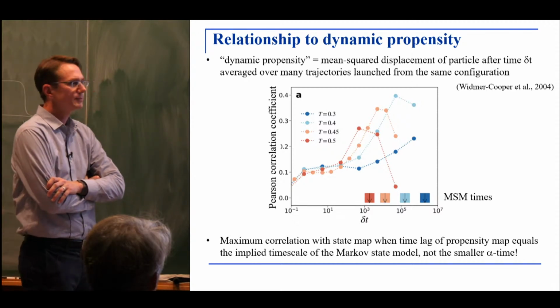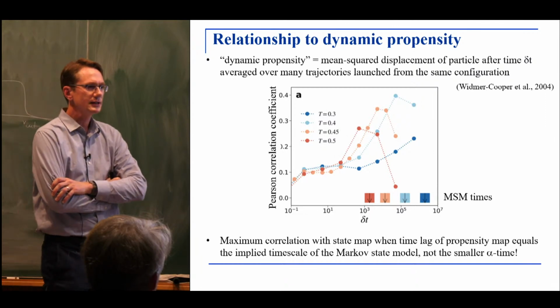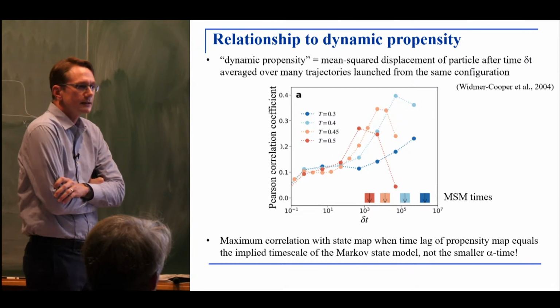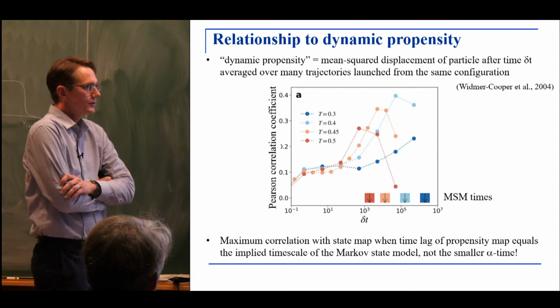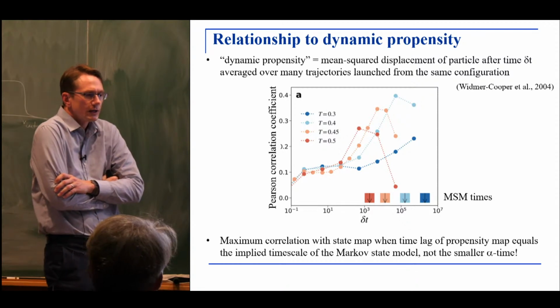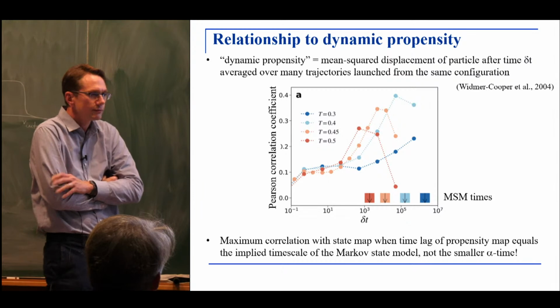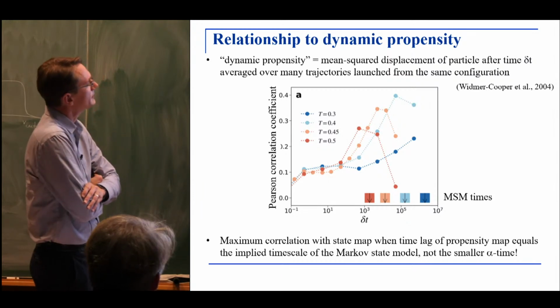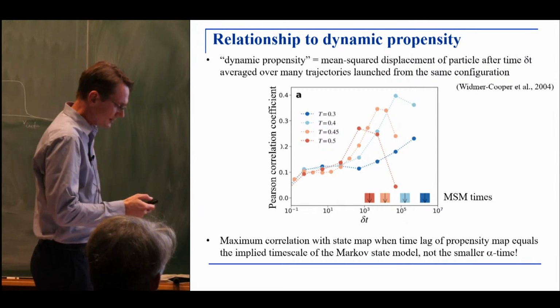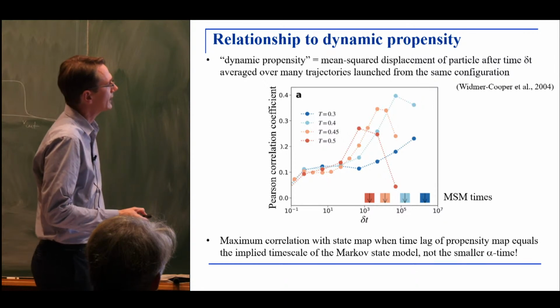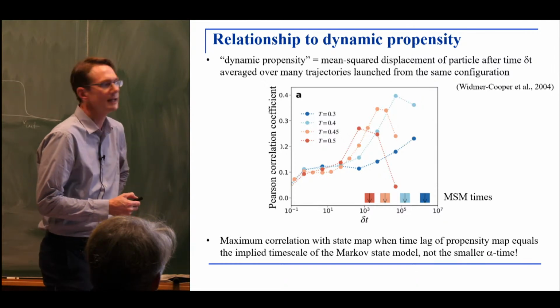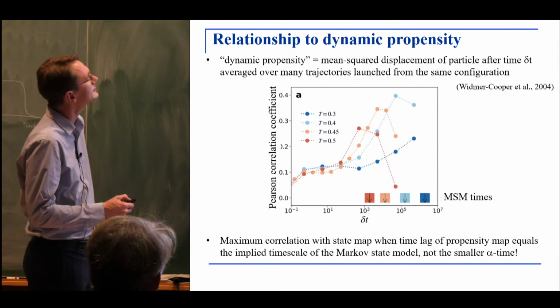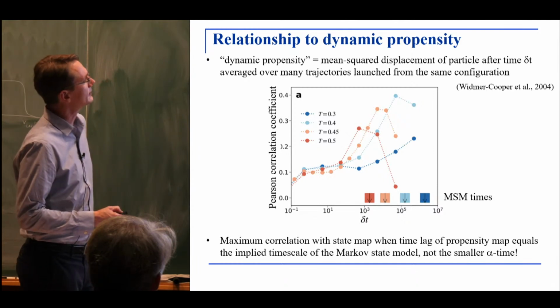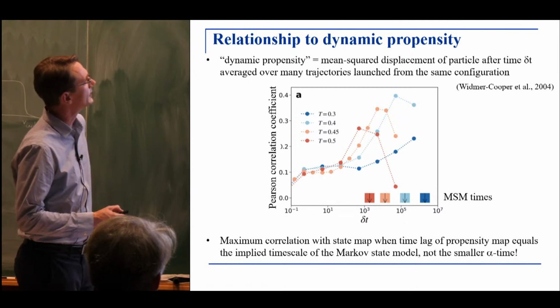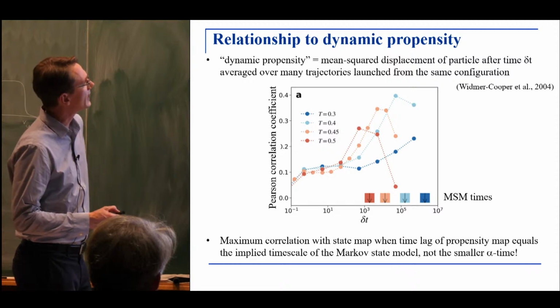But since there have been several papers that looked at this particular quantity, we thought we would simply calculate the relationship between our newly found state map, now also equivalent to the map of local Voronoi volumes, and the local propensity. We've done this as a function of lag time, delta t. Now, I think it's been explained to you what the local propensity is. You see here that all these curves, at different temperatures, reach a maximum.